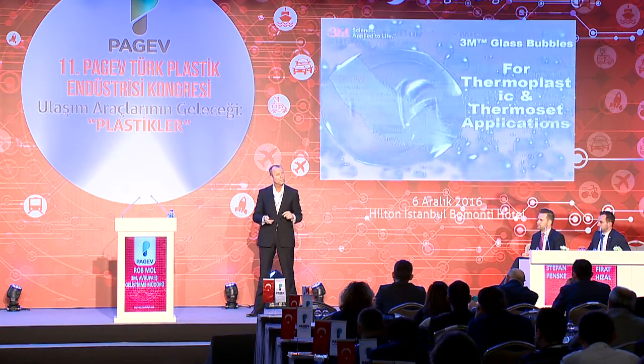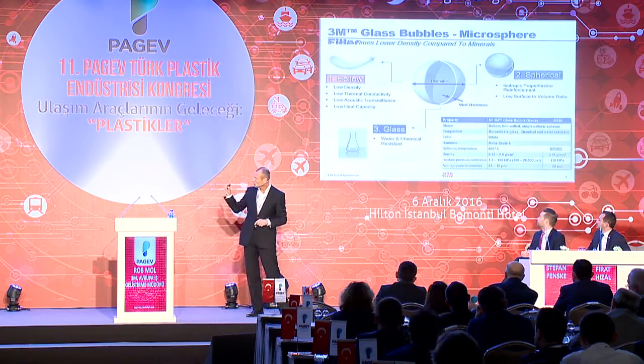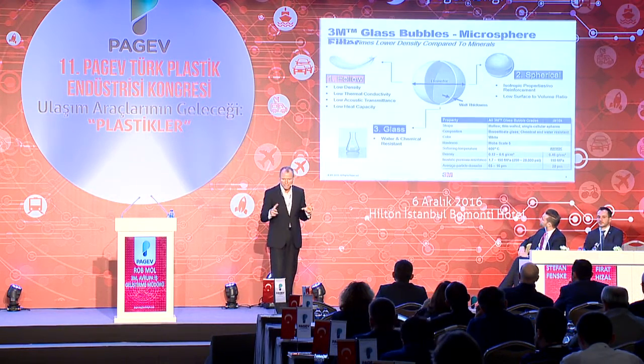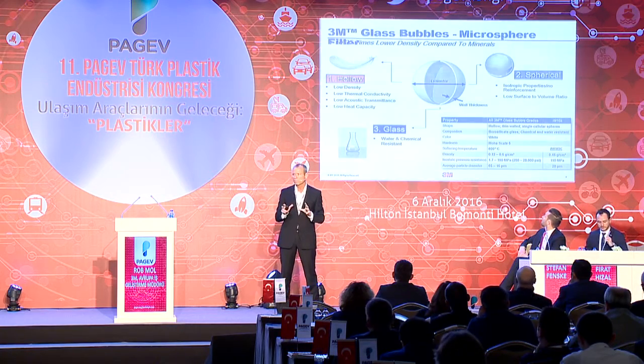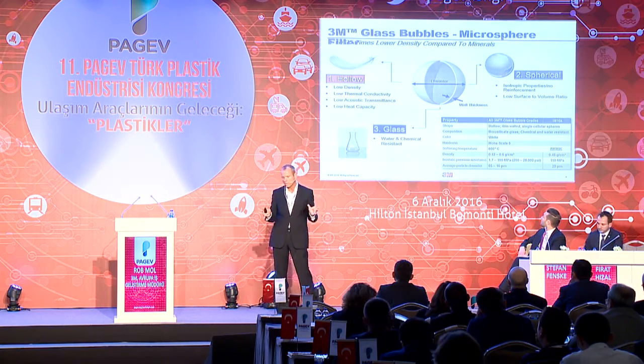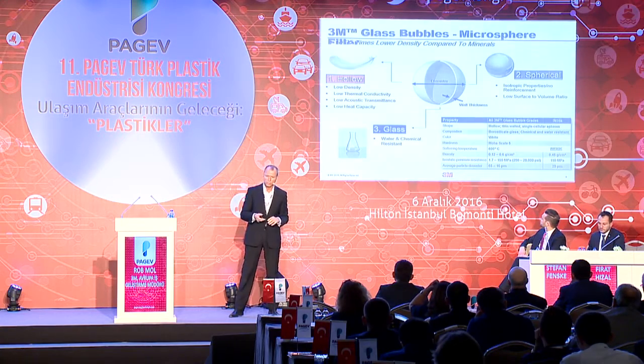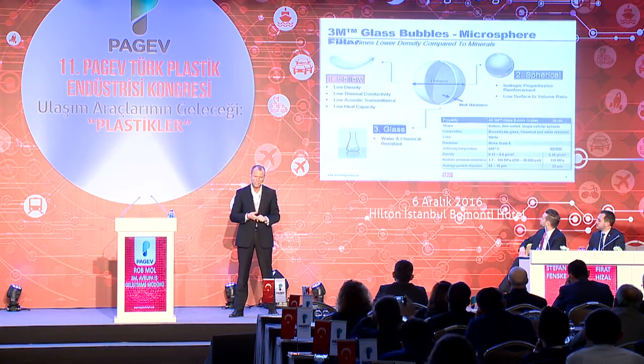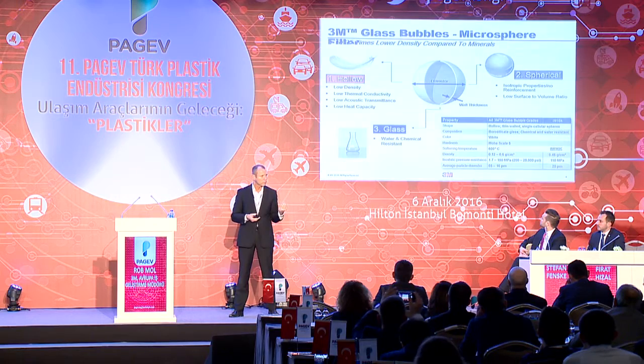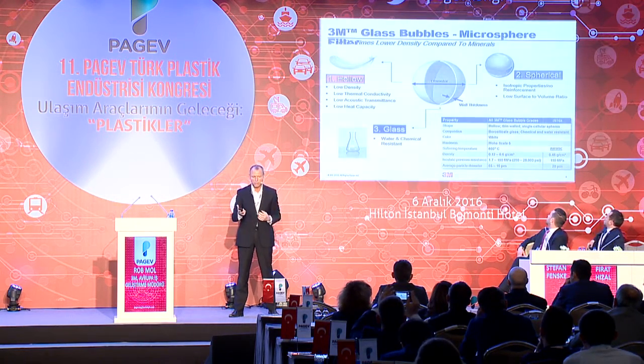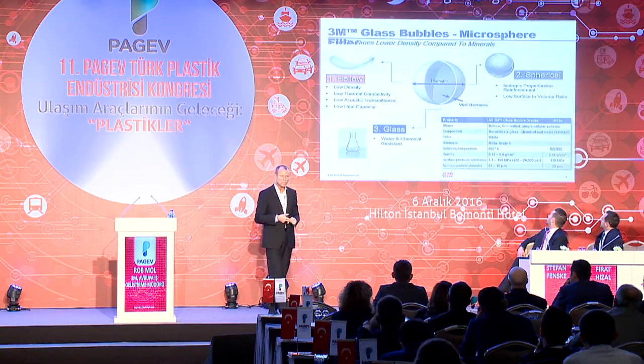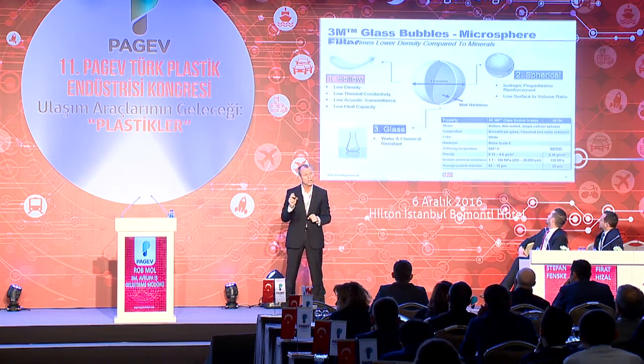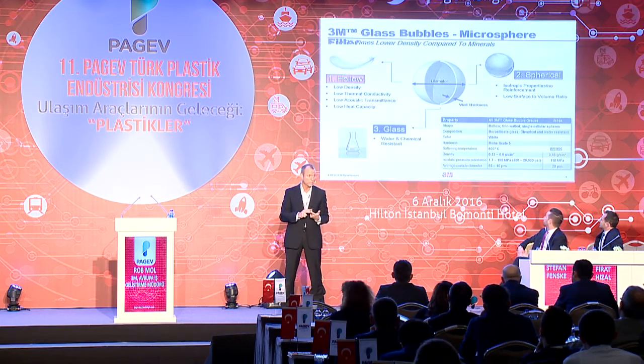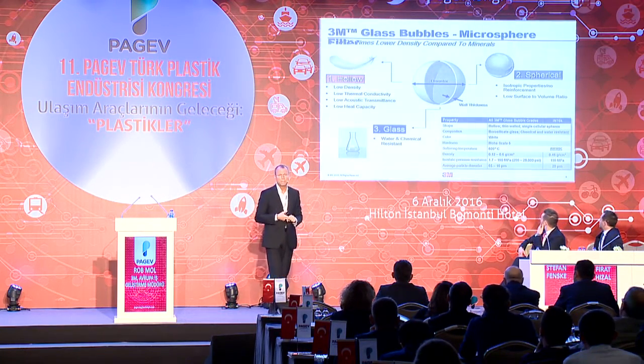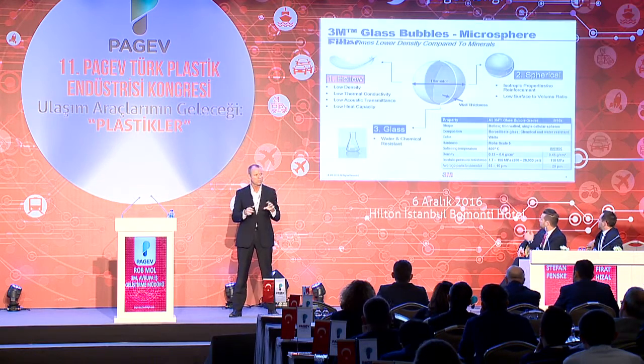So I will give you a little bit of insight into what it technically is and what it does, and then I will give you some examples where it's being used, because it's quite new and I think it's important that you understand what the applications are. If you look at it like this, it looks like a powder. If you put it under a microscope, there are very tiny particles that are hollow, that are spherical, with an aspect ratio of 1, and they're made of glass. So those are the 3 main features of this material.